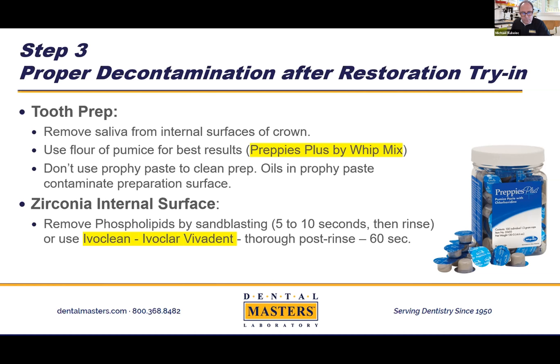I will say in reviewing the literature that the sandblasting is going to achieve about 30 megapascals in immediate bond strength relative to about 45 megapascals of bond strength by virtue of using the Ivoclean. So you're going to get a superior bond by virtue of proper use of the Ivoclean.